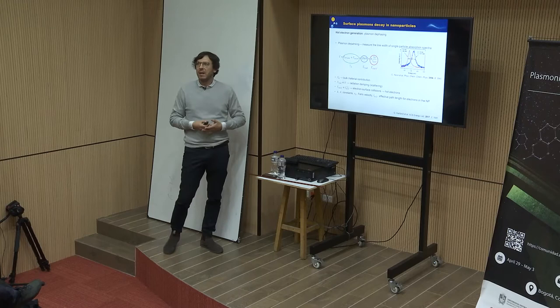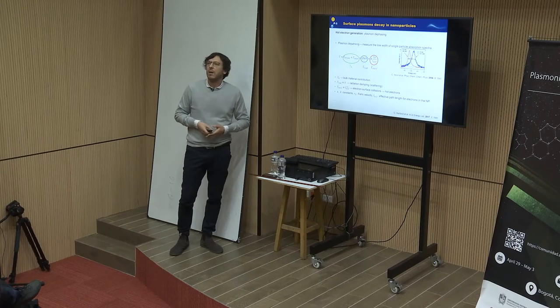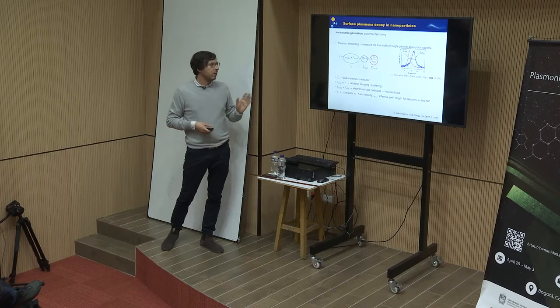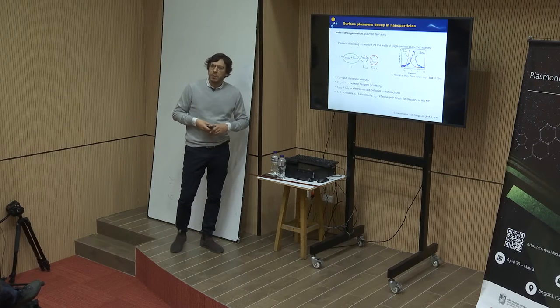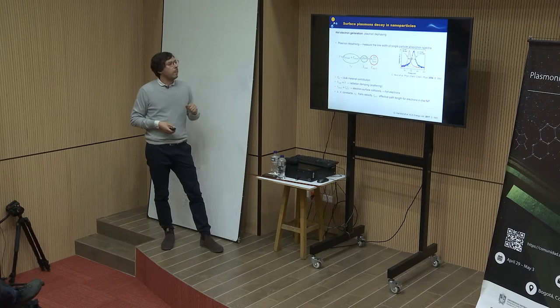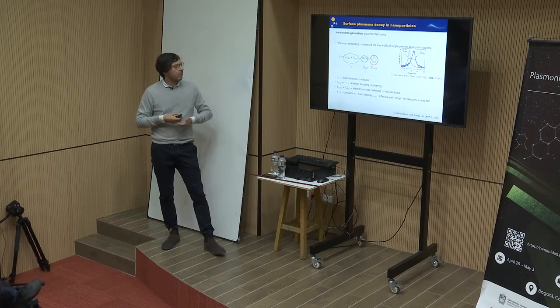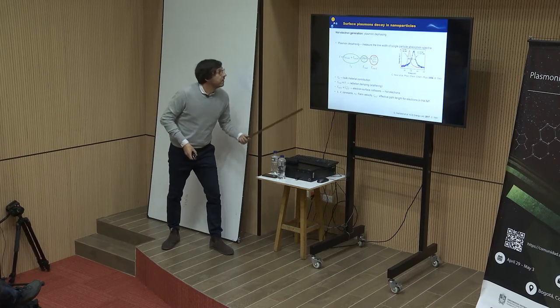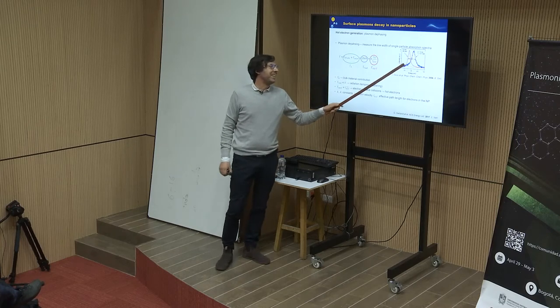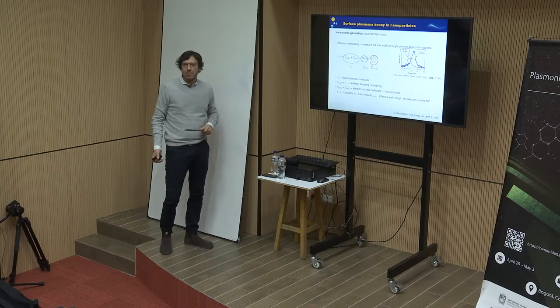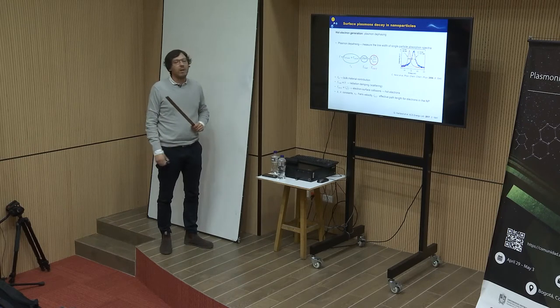So what we can ask ourselves is how we can measure this dephasing of the plasmons. For particles, it can be done, specifically in the last 20 years with the development of optical microscopy. We can measure the scattering from single particles, and so we can retrieve the optical absorption of our system. And so from the line width, for example, of our spectra, we can retrieve the lifetime, the dephasing time of our plasmon.